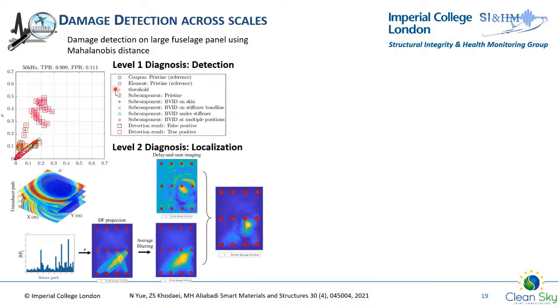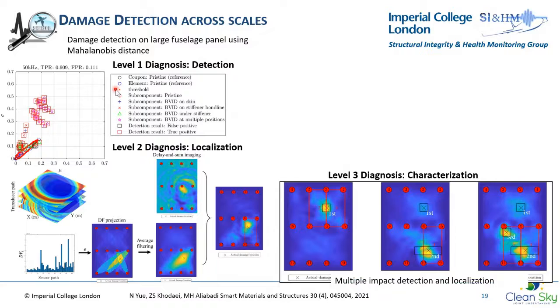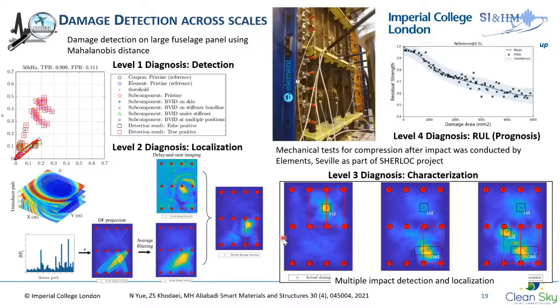And level two is then localization. There are very established localization algorithms such as RAPID, delay and sum, some combined with weighting residual. So we've used, we calibrated some of these imaging algorithms to detect impact, but also to be able to detect multiple impacts. So by grouping the sensors, you can see here that we've detected multiple impacts, and these are the result of damage localization at the subcomponent level, which is the flat stiffened panel.